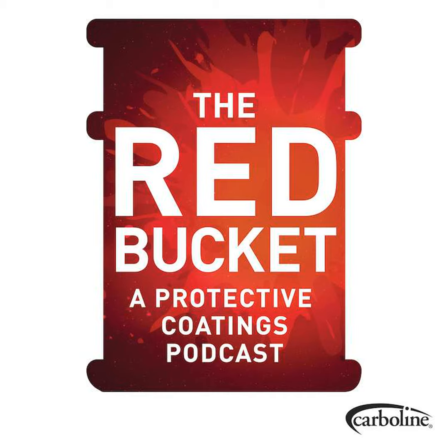Typically, when we're looking at color and gloss retention, UV protection on something like an elevated water storage tank, it really runs the gamut. Basically, you're starting with real super old school alkyds. Then you can move into some acrylic-based formulas. Could be water-based, could be urethanes. Then we move into the aliphatic urethanes, which really also runs the gamut of color and gloss retention and UV protection. We have some real bargain basement aliphatic urethanes all the way up to super advanced, pretty good performing aliphatic urethanes. You've also got polysiloxane technologies, which do a really good job of color gloss retention, chemical resistance, UV protection, some higher film build. But yeah, absolutely at the top of the order would be fluoropolymer top coats.